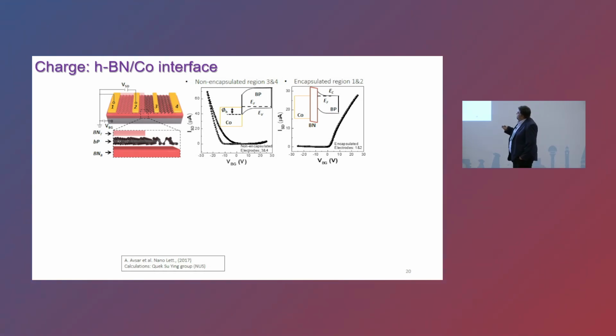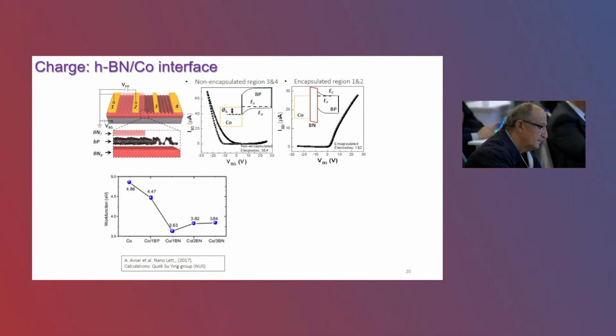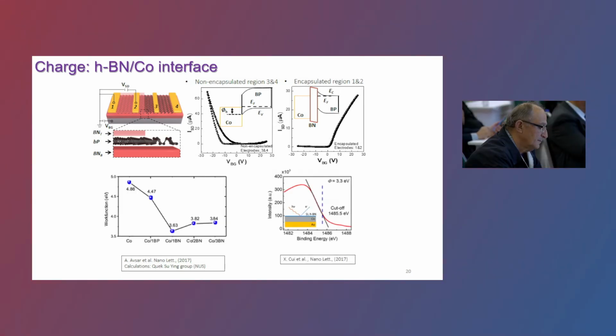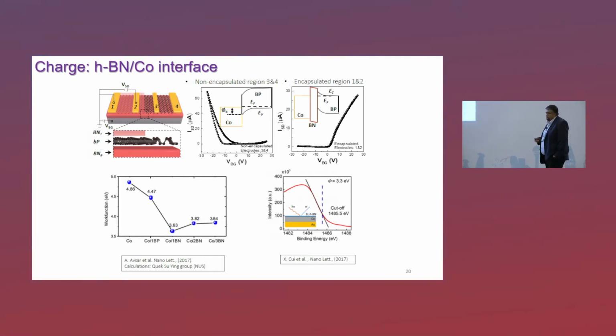For example, here, in the area where there is no hBN under the cobalt, you have this typical p-type behavior of black phosphorus. And whenever you study the device with 3 layers of hBN underneath, the transistor becomes an n-type transistor. We have done some calculations with our collaborator, Quek Su Ying. And what happens is indeed that the effective work function of cobalt is reduced if you insert a thin hBN.